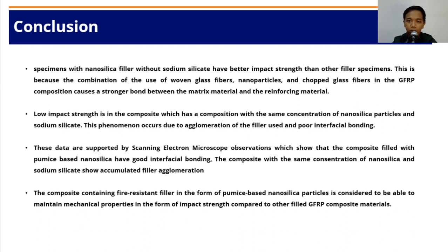This is because the combination of the use of woven glass fiber, nanoparticles, and chopped strand mat in the GFRP composition causes a strong bond between the matrix material and the reinforcing material. A low impact strength is in the composite which has a composition with the same concentration of nanosilica particles and sodium silicate. This phenomenon occurs due to agglomeration of the filler used and poor interfacial bonding.